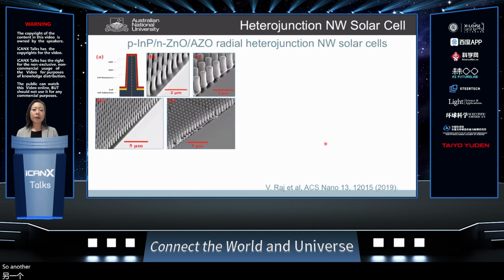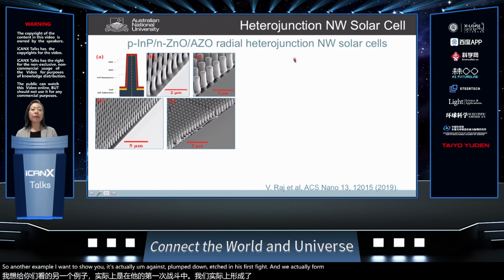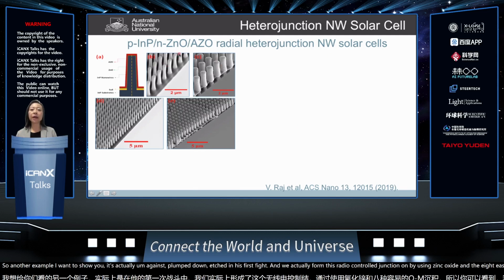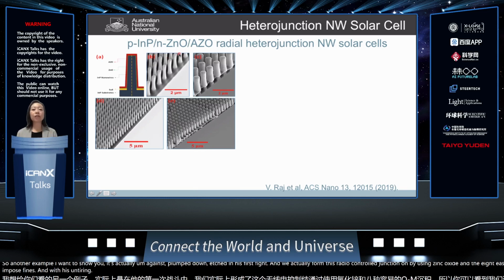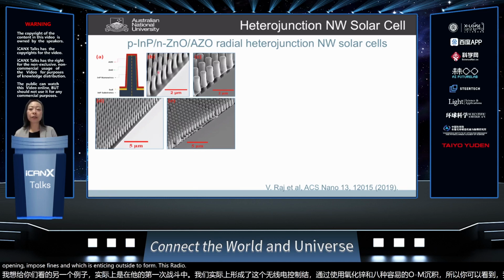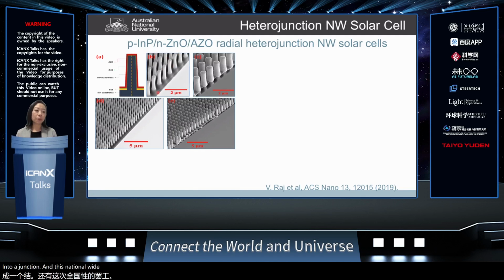Another example I want to show you is, again, top-down etched indium phosphide, where we form a radial heterojunction by using zinc oxide and AZO deposition. You can see that we use p-type doped indium phosphide with n-type zinc oxide to form this radial heterojunction, and this nanowire structure has been optimized in terms of light absorption.